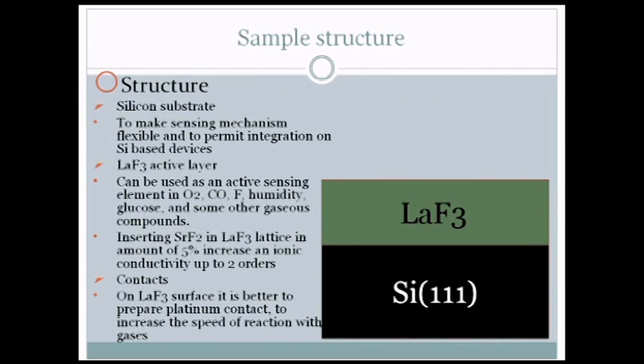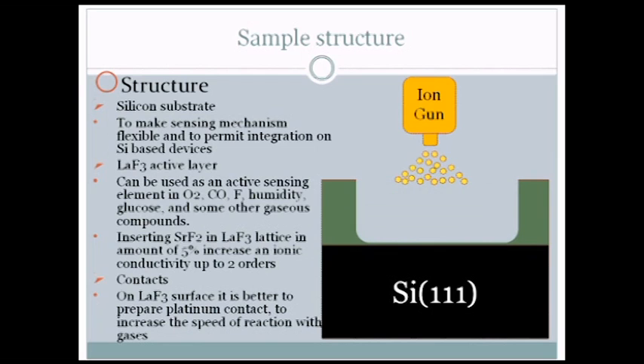Through our activity quite a big amount of structures was prepared, but here the simplest one is presented, lanthanum fluoride on silicon 111. Different mixtures were also prepared with, for example, strontium fluoride, which shows preliminary results of increasing of ionic conduction in this film by up to 2 orders. And to understand the structure of the lanthanum fluoride film on silicon, sputtering was used to obtain spectra not only on the surface but also in the middle and at the interface of the film.